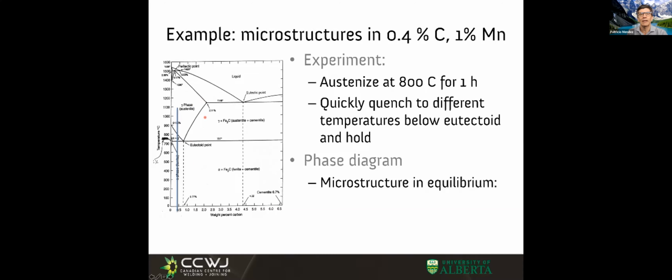And we saw that when the carbon is in excess, it doesn't precipitate as graphite flakes. It doesn't precipitate as chunks of coal. Graphite precipitates in the case of cast irons, but we're not going to be worrying about that right now. We're going to be worrying about steels. And in steels, the way it precipitates is in the form of a kind of ceramic or some sort of intermetallic. It's Fe3C, cementite. It's a very complex compound, and it's hard and brittle.